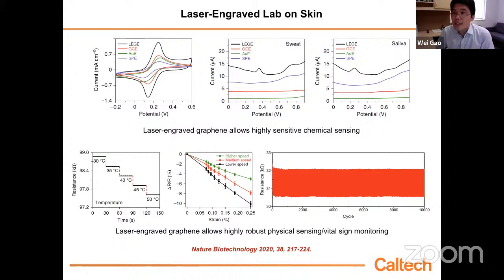But some people might think, since you're engraving or burning polymer to fabricate this 3D graphene structure, this structure may not be very stable. If you bend, things may fall off, which is not very true. If you control the parameters properly, the graphene structure on polyimide is quite robust.